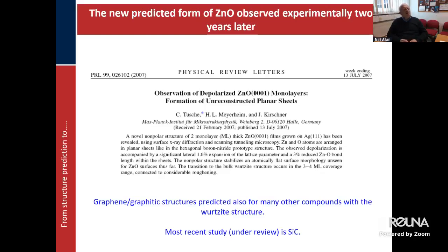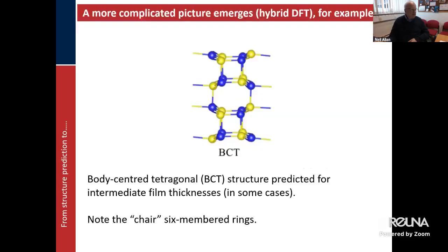And of course, we went on and developed that by looking at a lot of other compounds with the Wurtzite structure, apart from zinc oxide. We looked at zinc sulfide, other sulfides, other oxides, all behaved rather similarly, potentially forming these graphene-like thin films. And the most recent study, which we've been doing with Sergio, has been actually on silicon carbide and on the energy landscape of these thin films.